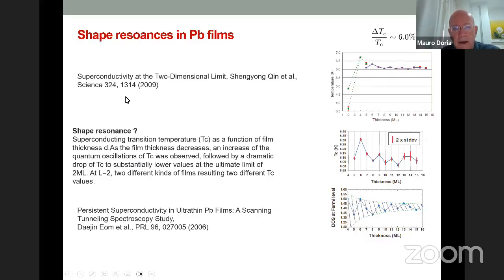And this was claimed to have been found by Qin and collaborators in 2009 in lead films. So here you see the temperature versus the thickness according to the number of layers, the monolayers.